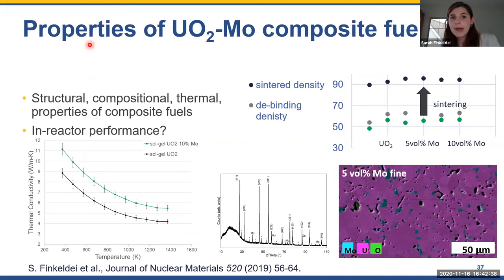So talking about a composite fuel, I have added molybdenum, which has a much larger thermal conductivity than uranium dioxide, to a uranium dioxide pellet. And what we observed was a composite fuel with molybdenum islands in the uranium dioxide.